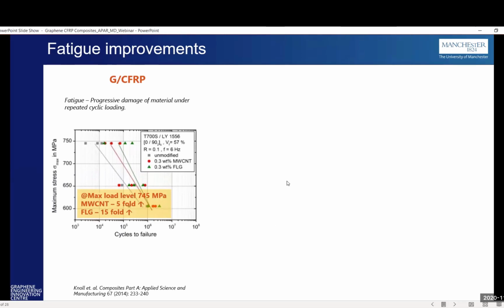So fatigue is nothing but a progressive damage of material under repeated cyclic loading. It is when a material is deformed under the elastic deformation levels. Because of the nature of it being deformed, there's a debonding that can happen between the matrix and the fiber or the reinforcement, which creates micro cracks, and these micro cracks can eventually become macro cracks, and the crack can actually propagate, which eventually leads to the failure of the material.